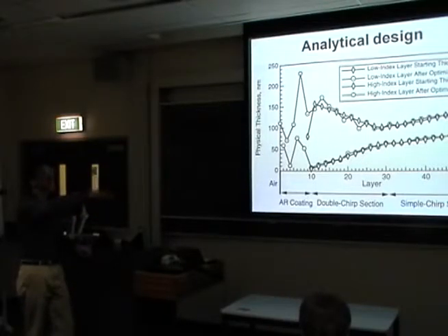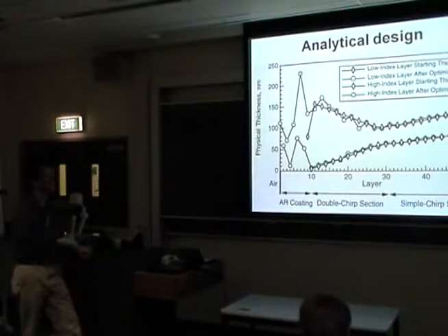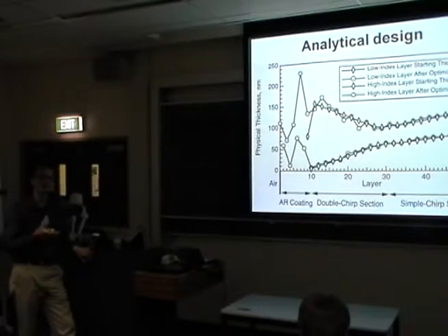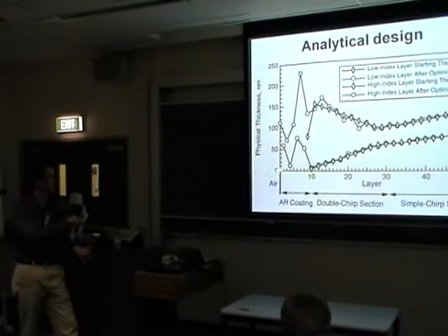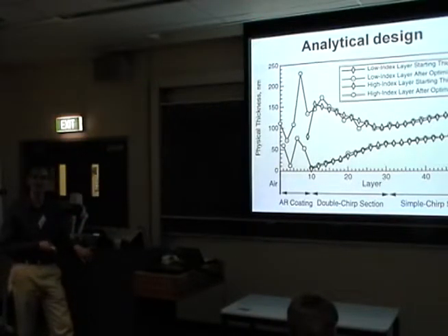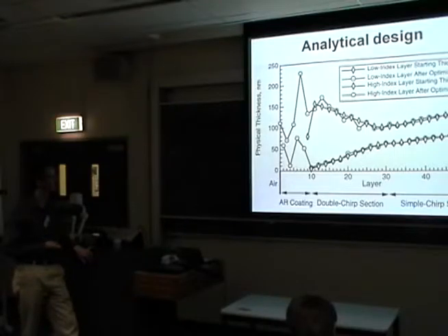So here I have a Bragg condition where the red light gets reflected in here, very deep inside. And here I have shorter wavelengths, so my blue light gets reflected already here. And here is again this trick where we cheat the photons into believing that they are actually propagating only in low-index material. But you see that actually these thicknesses are ridiculously small. It's only about 10 atom layers. And so that's kind of the hard part to make those things work.